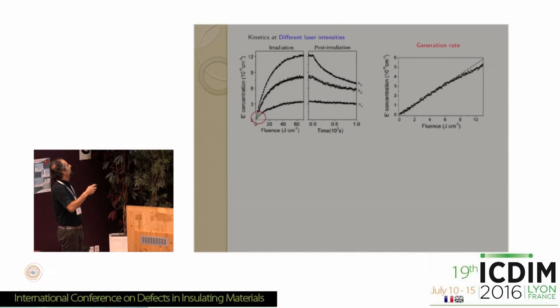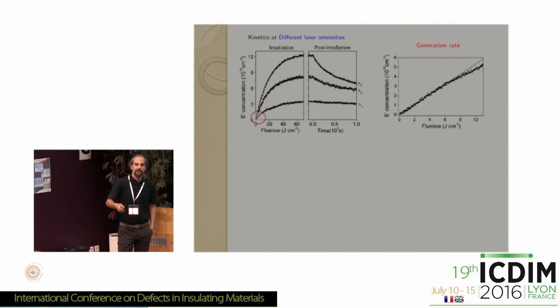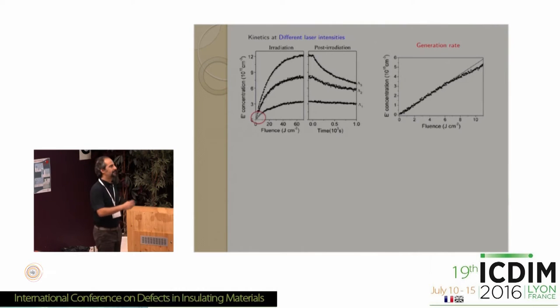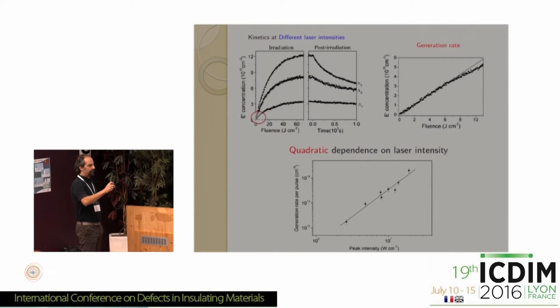Then we examined another aspect of this kinetics. Let us look again at the kinetics obtained at different laser intensities. If we now concentrate our attention on the first steps of the generation, we can extract a generation rate for the defects. So the efficiency by which the laser generates the defect is related to the initial slope of these curves. And if you plot this as a function of laser intensity, what you see is that the dependence is not linear.